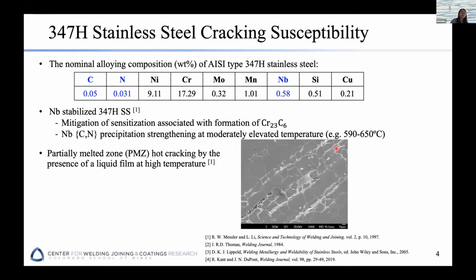But adding this niobium carbon nitride has some problems associated with it. For example, during welding, in the partially melted zone that is immediately adjacent to the fusion zone, you will have a liquid film forming. Those white features in there are typically the niobium carbon nitride eutectic phase that has a lower melting temperature than the base material, and that will form a liquid film and cause the cracking issue.